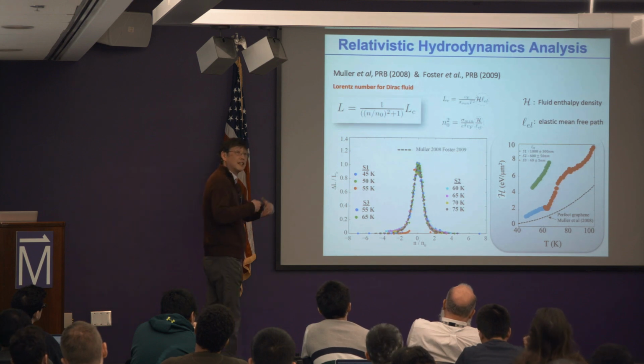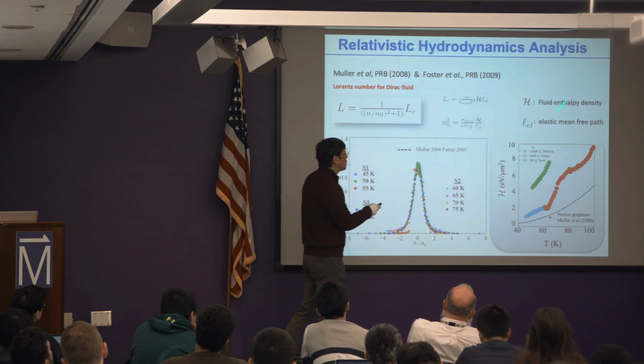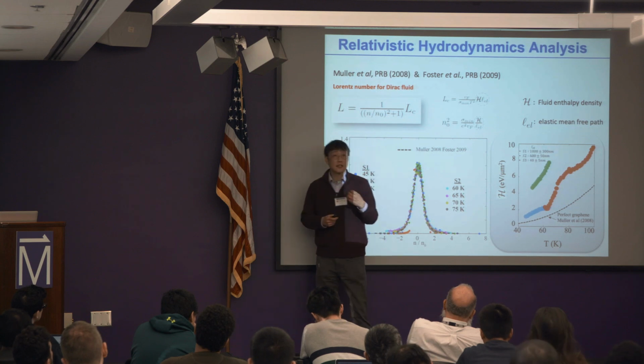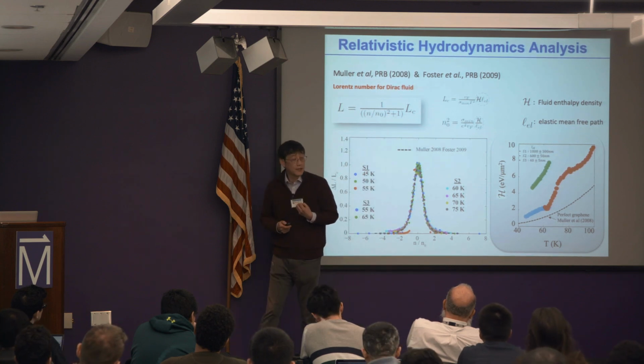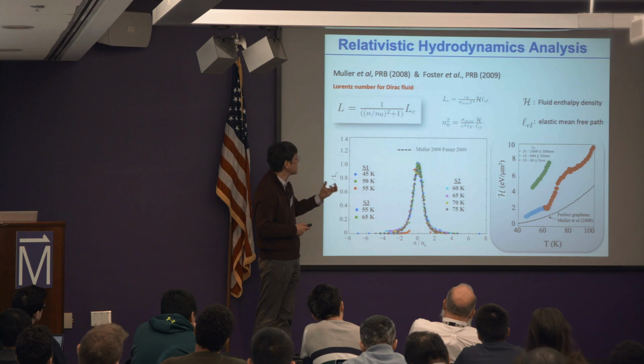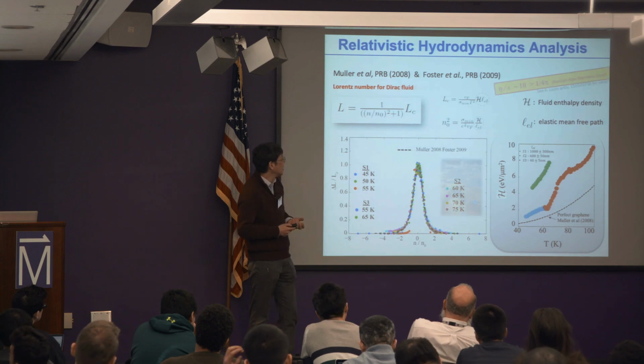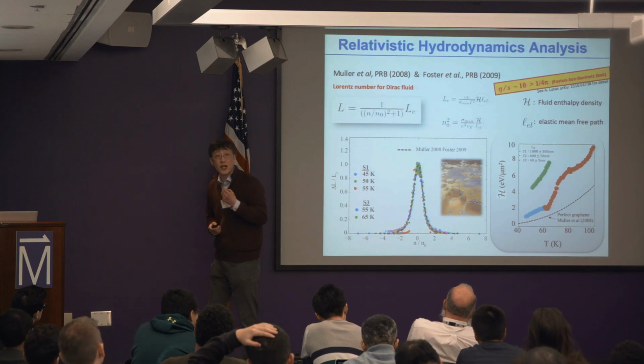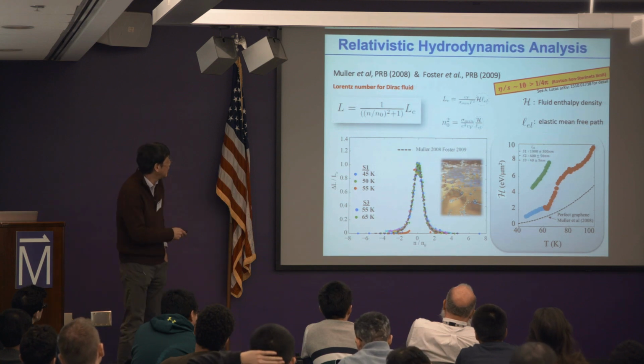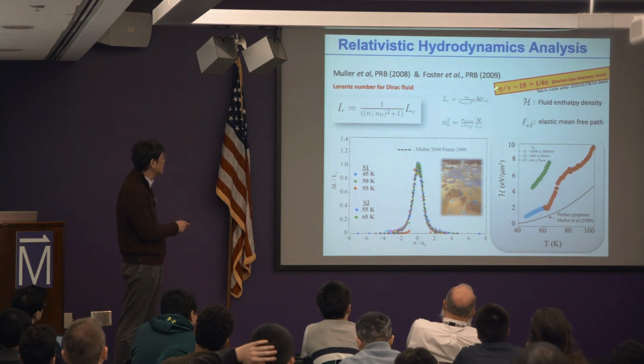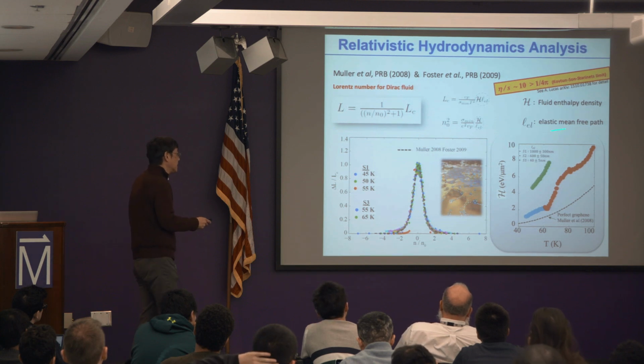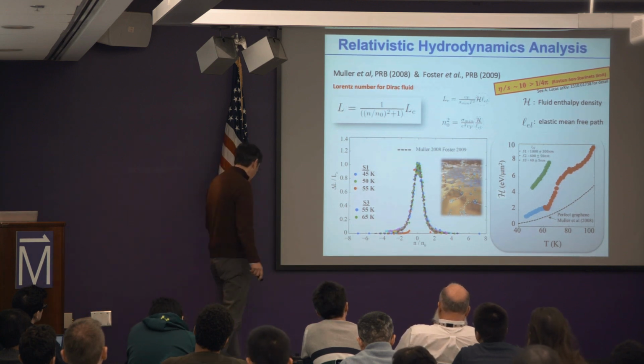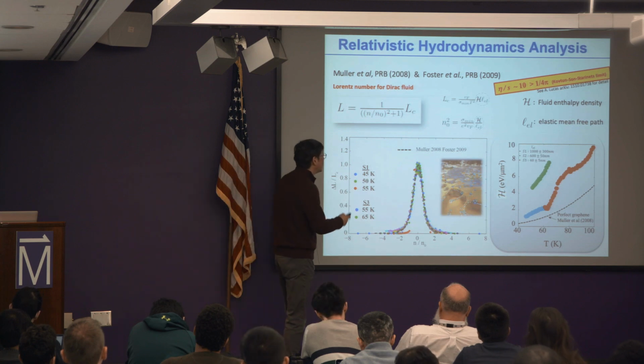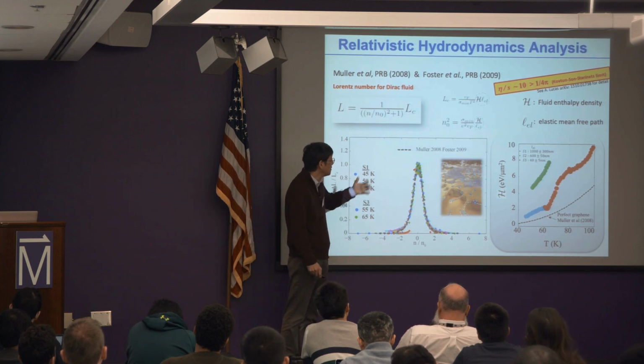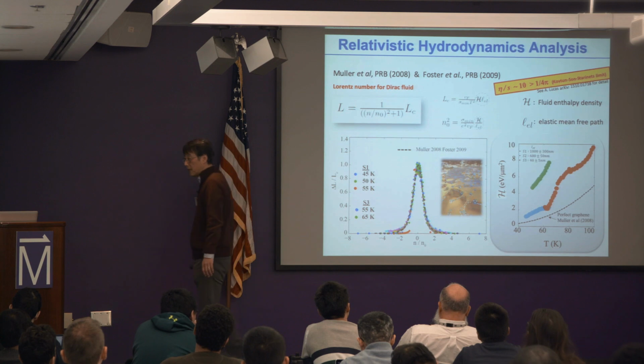So at least we start to see that some of the description is working. If you push this idea even further, the enthalpy of this fluid is also related to the entropy of the system and the viscosity. There's a nice relation in fluid dynamics: take the ratio of viscosity to the entropy of the system. A minimum bound exists, and it seems that this system satisfies these bounding values. So there are more things we can push on.